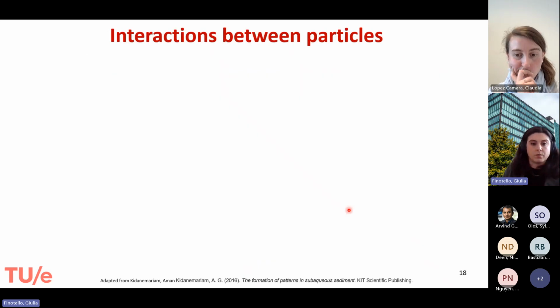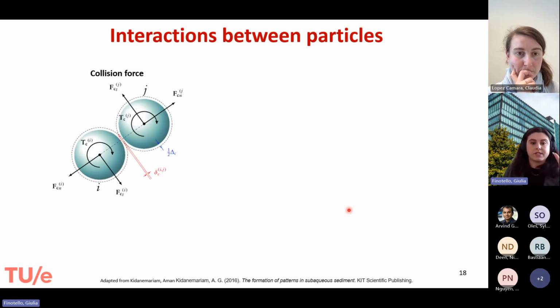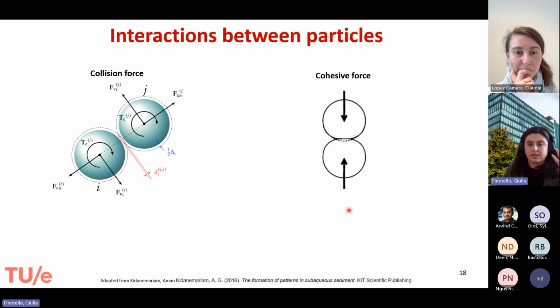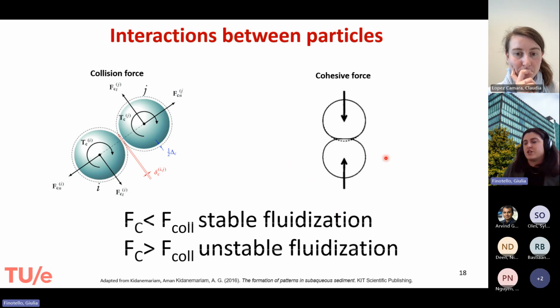So although this is a very complex mechanism, we looked a bit into that, and this is, of course, due to the interaction between the particles, and more about the balance between the collision forces and the cohesive forces. So cohesive forces tend to make the particles stick together, and collision forces are the forces of collision. If the cohesive forces are smaller than the collision forces, then we have a stable fluidization. If the cohesive forces are larger than the collision forces, then we have an unstable fluidization, which can end up in a full defluidization.